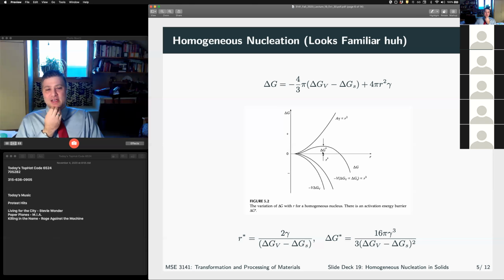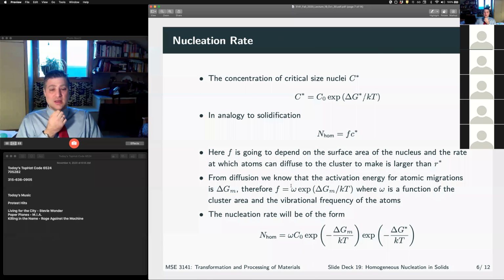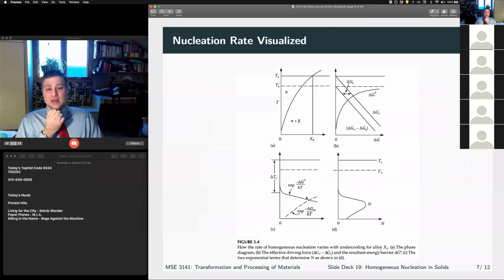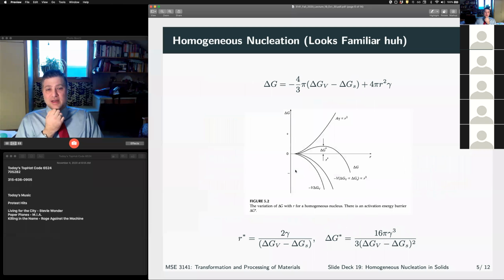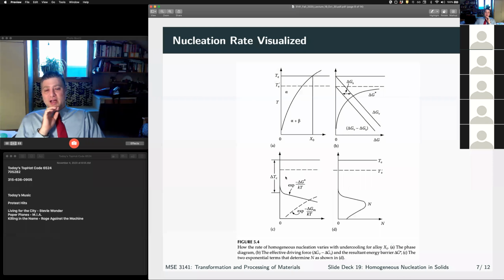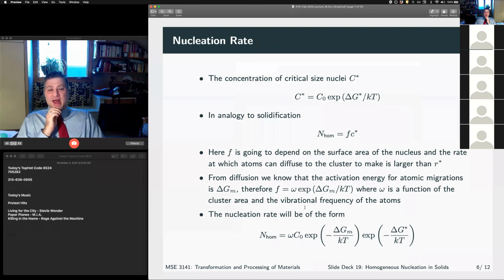We have an activation hump that's given by delta G star. We have a minimum stable cluster size that's given by R star, right? This is exactly the same. The only other difference is with the rate, right? Because we have a diffusion term. We have to consider the fact that atoms need to move. We don't have perfect mixing or fast diffusion like we had in a liquid. In the solid, we have a much slower diffusion. We have to take that into account.